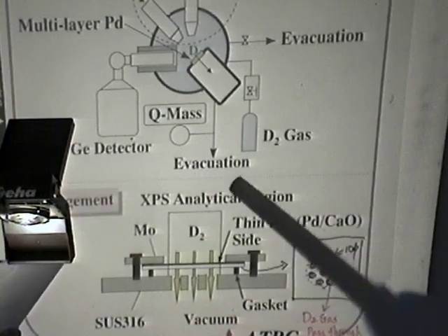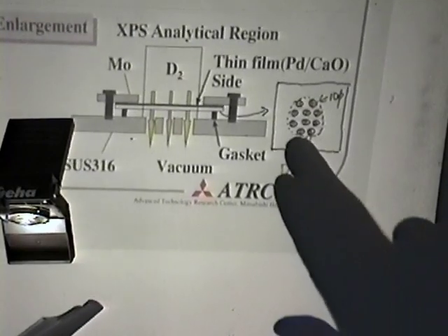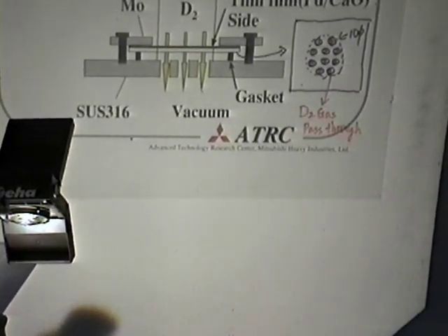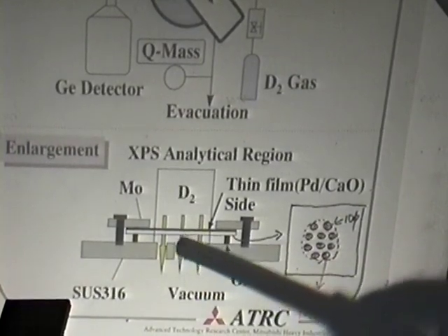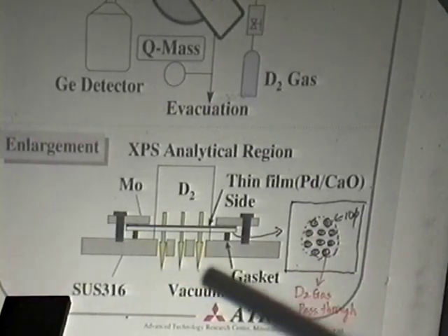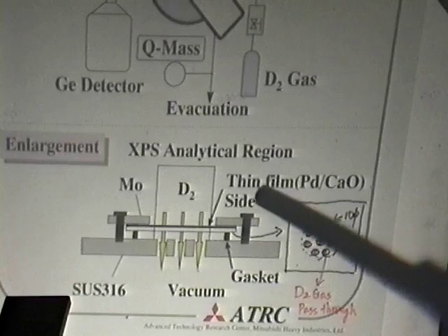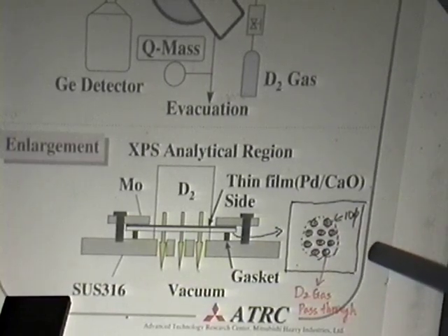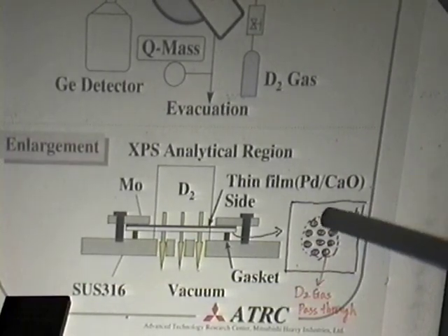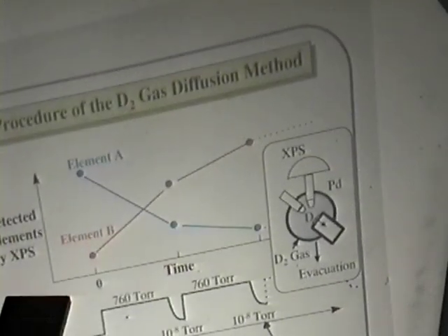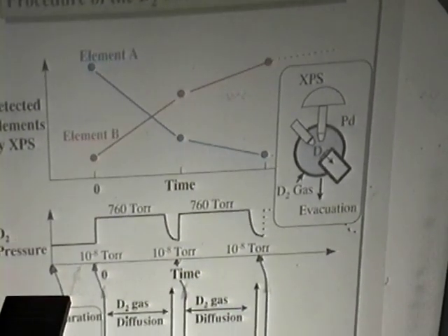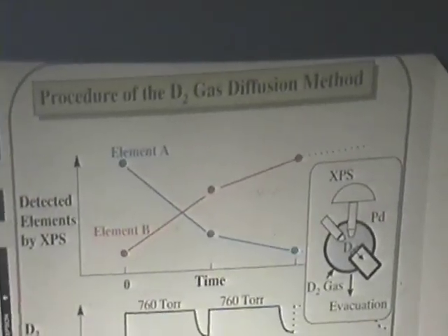This figure shows an enlargement of the multilayer palladium. D2 gas on the upper side, and vacuum on the lower side. D2 gas and vacuum are divided by this multilayer palladium and this gasket. The thin film side of the multilayer palladium is the upper side. This is the top view of the multilayer palladium. D2 gas passes through this red region. Next, we explain the procedure of the D2 gas diffusion method.